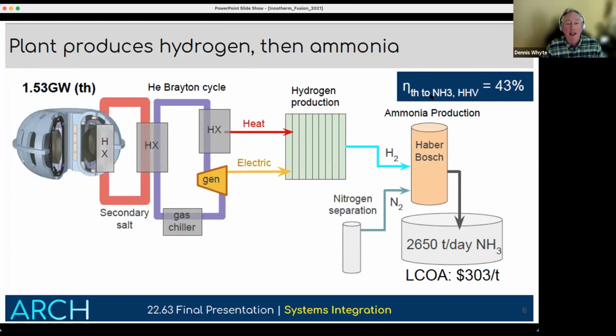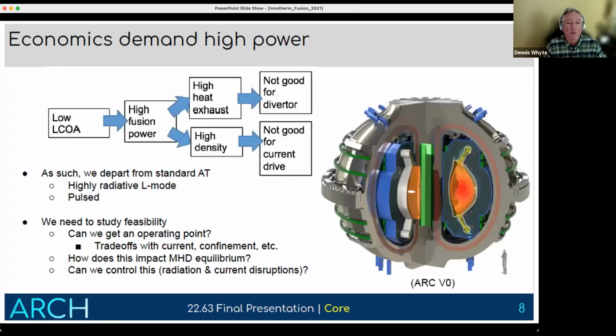But what did this take? Again, this isn't too much of a surprise: in an energy source that has no fuel costs, your economics are almost solely driven by power density. And that's what we found, that as you try to get to a low levelized cost of ammonia, this really came down to two things: high heat exhaust, and high fuel density, which basically increased the fusion power density.